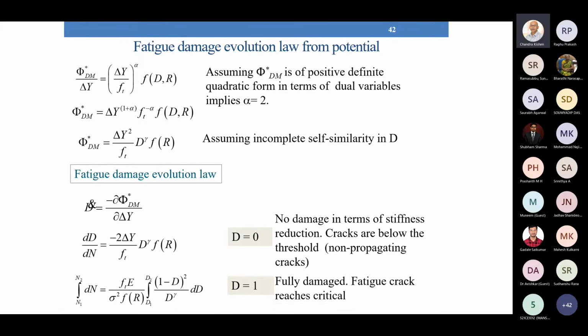And using dimensional analysis, we could obtain a relationship between the rate of damage and other physical parameters, including the material parameters, the loading parameters, and also the geometry parameters. The damage which we have considered is a scalar damage wherein 0 stands for no damage or no cracking or no reduction in stiffness, whereas D equal to 1 stands for fully damaged.